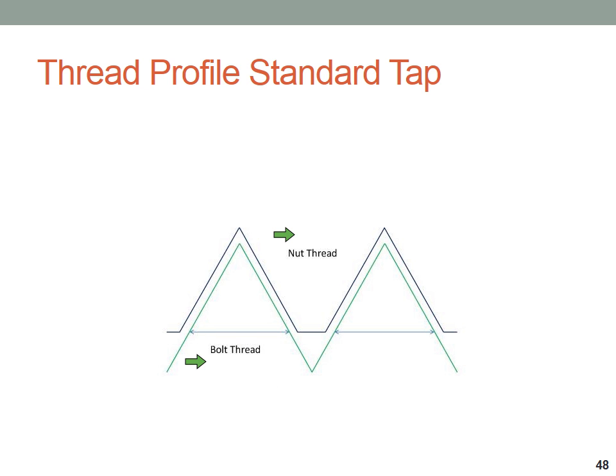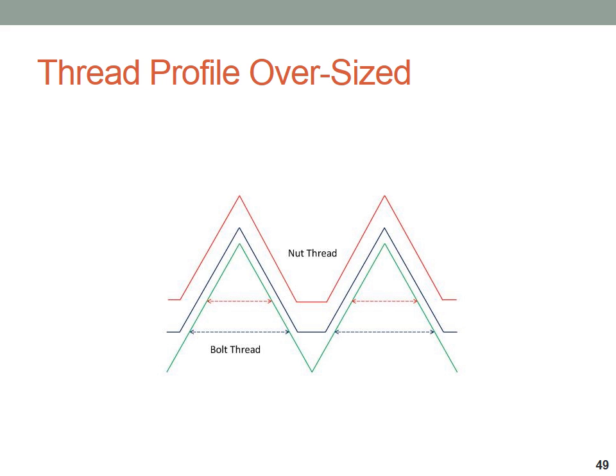Now, when we add coatings, they have a significant effect, because if you can picture measuring coating on a plate, for example, if you add coating thickness, it has a one-for-one relationship. The coating thickness is the coating thickness. If you add coating thickness to a cylinder, the effect on your cylinder is double the coating thickness, because you're measuring it on both sides. Since we measure pitch in 4 places, the effect of a coating on a fastener is that it has a 4-to-1 multiplier on the thread fit.